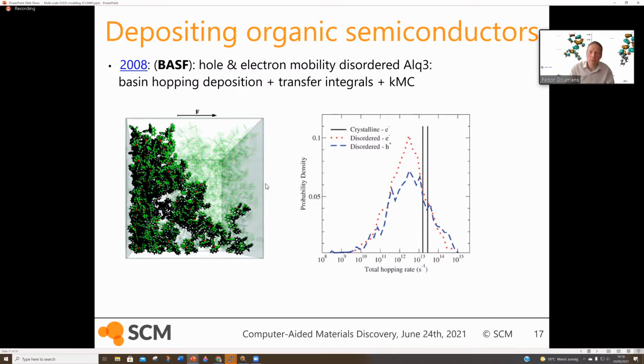So what we've recently done is implement our own deposition method, which is essentially based on a feature that we use for things like chemical vapor deposition, etching, these kinds of things. It's called the molecule gun. And it can be used in combination with an acceleration technique called force-biased Monte Carlo. And that setup can be used with anything that gives you forces and energy.